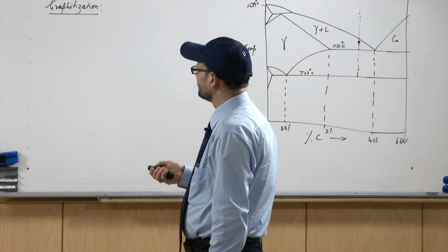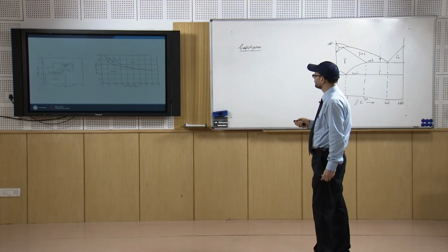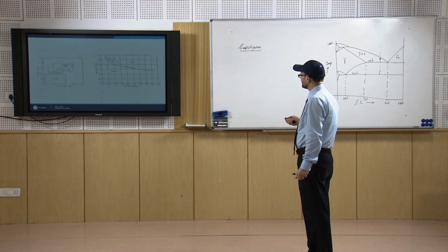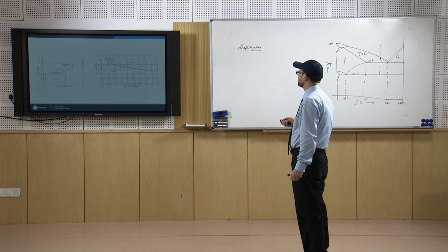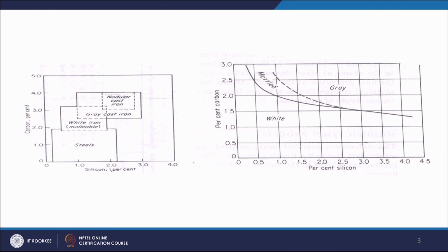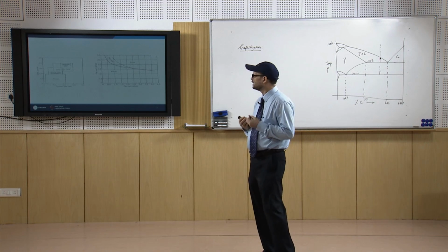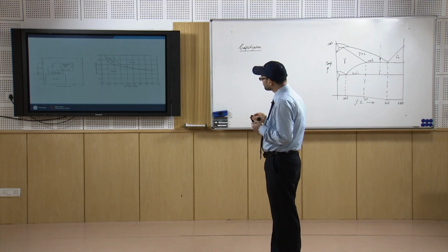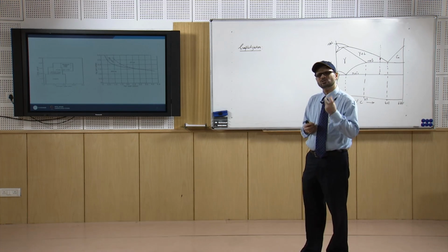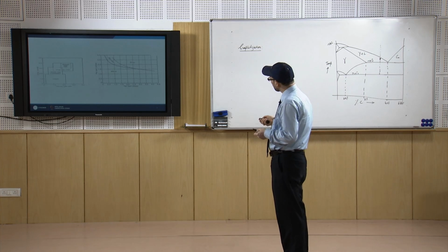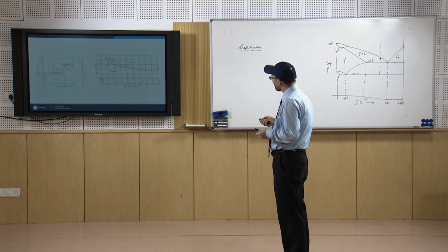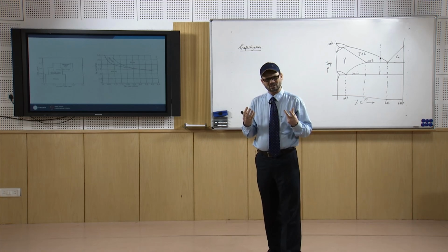This diagram further tells how you get the different varieties of cast iron. What we see is when the silicon is higher and carbon is higher, you get the gray iron, and when you have these smaller quantities you get the white iron, and in between you get the mottled iron. And if the cooling rate is maintained at a low value, in that case this curve will shift towards left. So, if the cooling rate is lower, then even at the smaller values of silicon and carbon, you may get the gray iron structure.